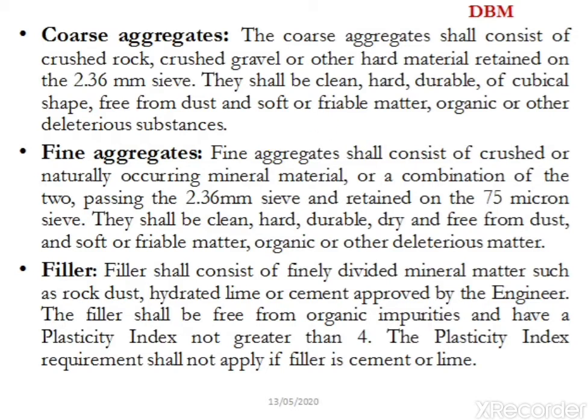The coarse aggregate used in the construction of DBM consists of crushed rocks, crushed gravels, or any other hard materials. The coarse aggregate shall be obtained from an approved quarry. One cone crusher shall be installed at the quarry site. This crusher shall produce aggregates of cubical or angular type so that flakiness and elongation index are contained within the specified limit. The coarse aggregate shall satisfy the specification as per the contract.